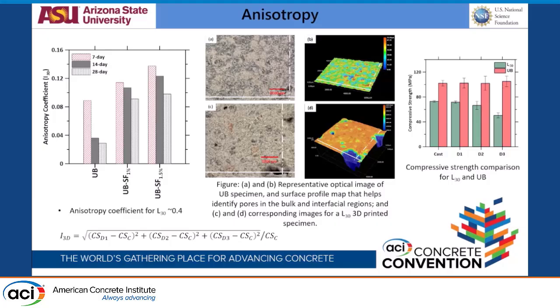For even with steel fibers, we are within like 0.1 at 28 days, in comparison to a normal strength mix, that's like a 70 MPa mix we use for our work in printing. We had an anisotropy coefficient of 0.4 in those samples when we did similar layer height, similar filament width printing, and we did a 3-directional test. We were in the range of 0.4. So we have a significant reduction in the anisotropy. Now, why is it so?